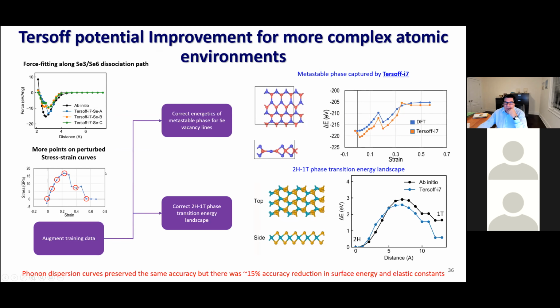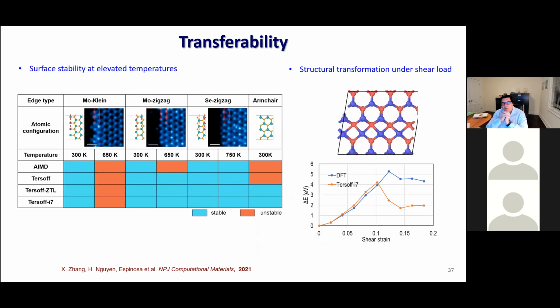That improvement that you see in the bond environment gave us much better prediction of the phase transition from the 2H to 1T, two phases in the material. You can see here the right energy of the phase at the end of the transformation, and the energy barrier is also well described. So many details that you want to use this calculation in a variety of scenarios. Transferability is a big thing because it means properties that you didn't fit, how well it does. And I can tell you that the different versions of the Tersoff that we parameterized behave quite well in capturing surfaces.